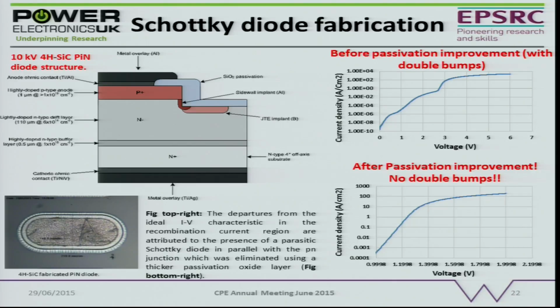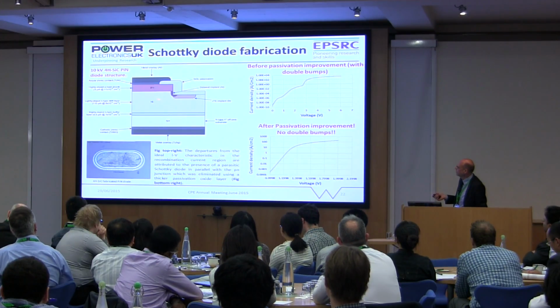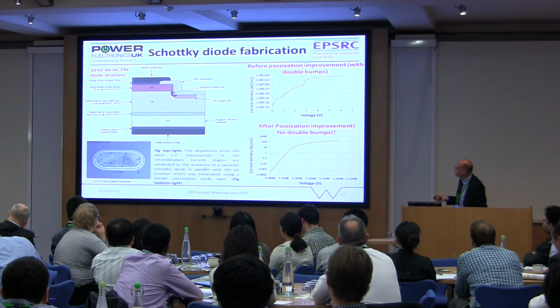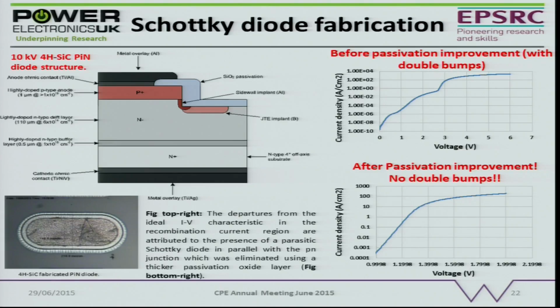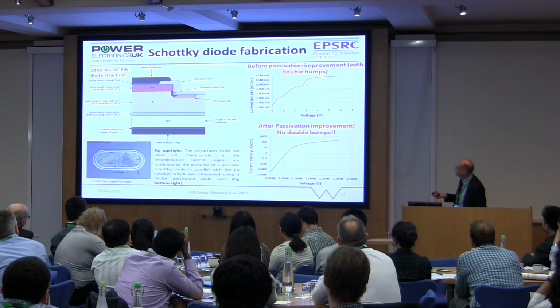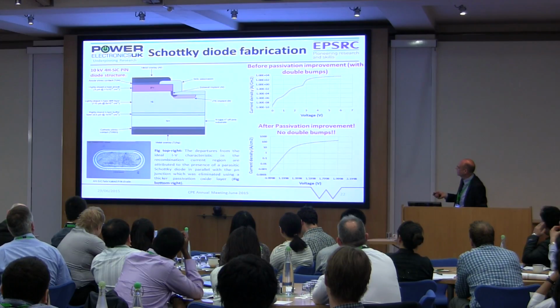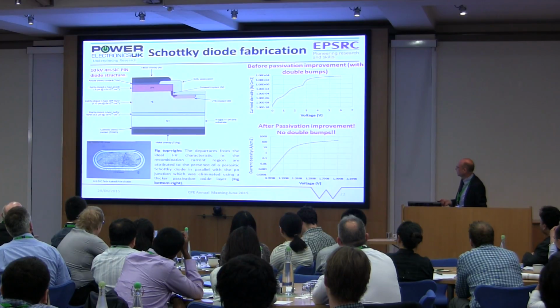So they're a mesa structure with all the doping here. All these different layers are grown using epitaxy. These bits here around the edges are implanted. We did quite a bit of trial and error here. The first few samples that we had had this sort of bumpy IV characteristic, but we found out that this passivation here wasn't quite good enough around the edge, and if you improve the passivation, you end up with very nice quality characteristics like that.